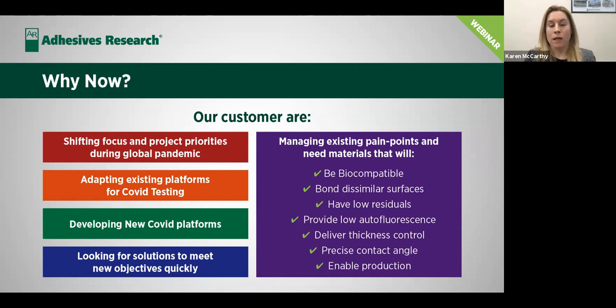Looking for tight thickness control. If the adhesive tape is to be used as a spacer within your device, the thickness of this tape would dictate the height of the capillary and thus the sample flow or the sample volume in your device. So it's critical that this is maintained at a tight thickness control and is consistent batch to batch.